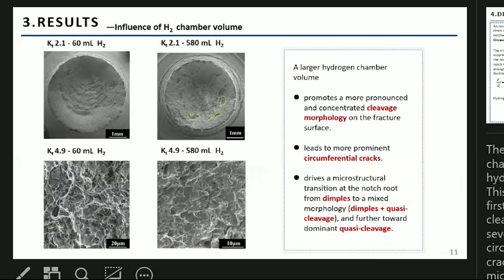The result in large hydrogen chamber volume showed more hydrogen embrittlement features. This is evidenced in three key ways. First, more pronounced localized cleavage features, second, more severe circumferential cracking, and third, a microstructure transition at the fracture edge from dimples to a mixed mode of dimples and quasi-cleavage, and finally to dominant quasi-cleavage. From this, we can deduce that the brittle features are driven by a synergy of hydrogen embrittlement and stress concentration. But when the stress concentration becomes high enough, it in fact overshadows the specific contribution of hydrogen. And this is why we introduced the concept of tuning stress concentration factor for engineering.